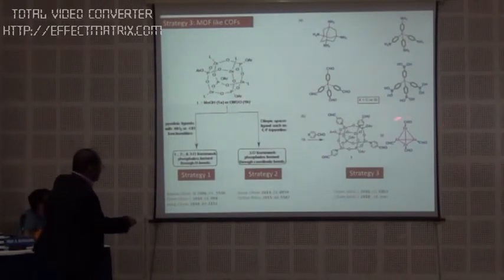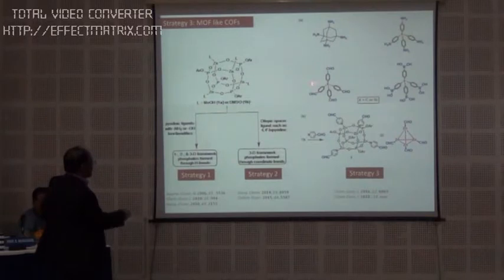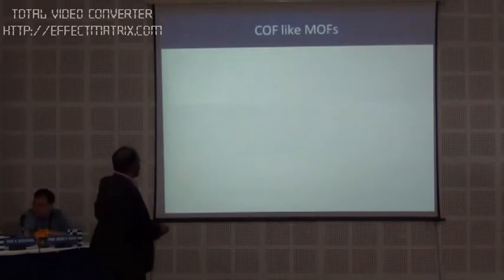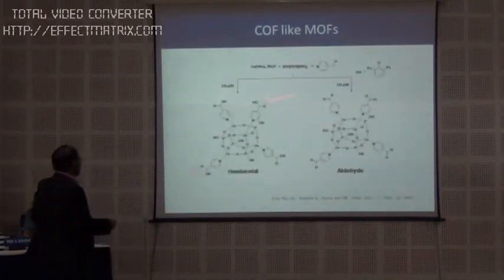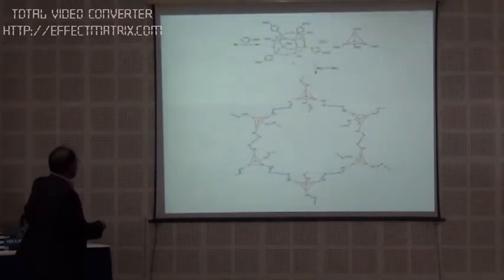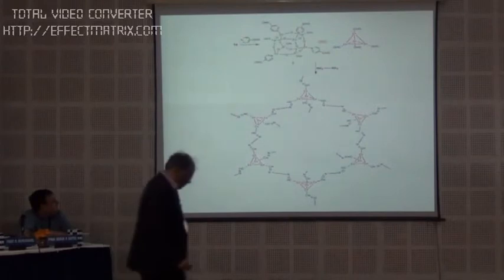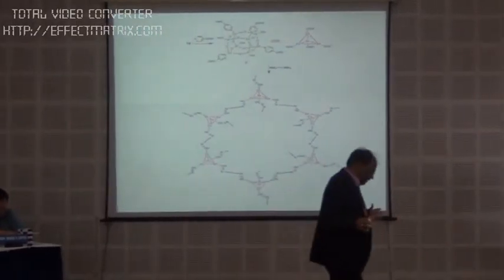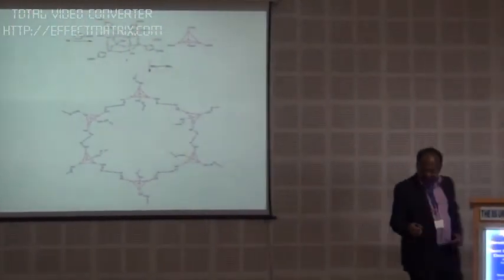But we saw our molecule was something similar to what has been described in the literature before, because there are 4 zinc atoms, this cubane, in the corners of the tetrahedra, and the 4 formyl groups are just protruding out. So exactly that's what we did. We took this molecule. This is the synthesis of this molecule. I'm not going to spend time on that, but to show that we took this molecule and then combined it with diaminobenzene and its higher congeners like benzidine and the substituted benzidine molecules.